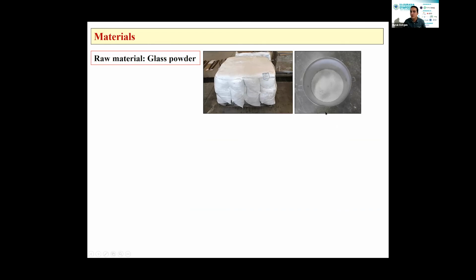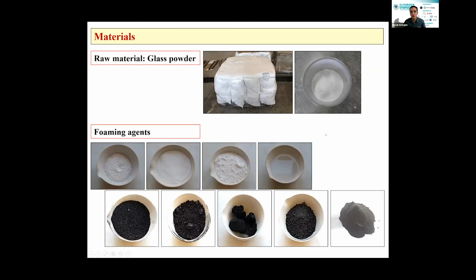The second is type 2 glass powder. We took our waste glasses in our university, and these are subjected to mechanical breaking, grinding or crushing processes, and it is the type 2 glass powder. And these are our foaming agents. We used a total of 10 different foaming agents, and 9 of them are given here. These are calcium oxide, dolomite, calcite, glycerin, and different types of coals, for example dust of oak coal.